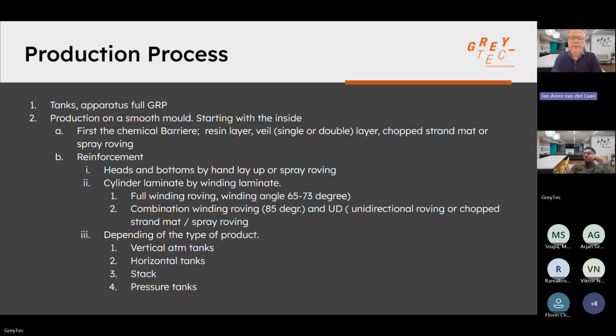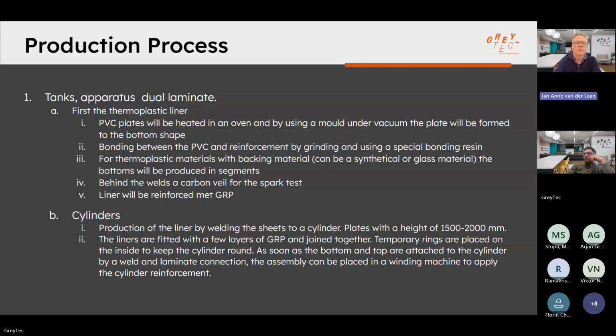For dual laminate products, the chemical barrier is provided by the thermoplastic liner. For example, for PVC liners, roofs and bottoms can be formed using heat and vacuum molding. The PVC sheet is heated in an oven and vacuum formed into the mold. The reinforcement is bonded by grinding the surface and applying the correct bonding resin. For other thermoplastics, the liner material is supplied with a backing material, such as glass or a synthetic fabric. Roofs and bottoms are produced in segments and reinforced with laminate. For quality control purposes, welds are covered with carbon veil so spark testing can be performed. Once the body is completed, nozzles and accessories are installed and connected using reinforced laminates.